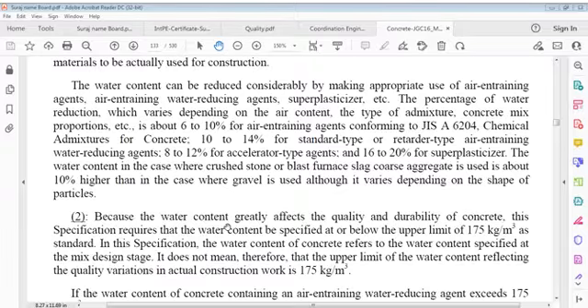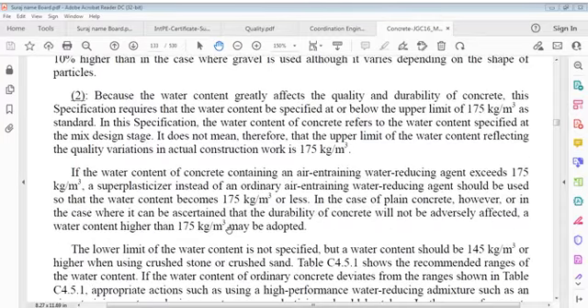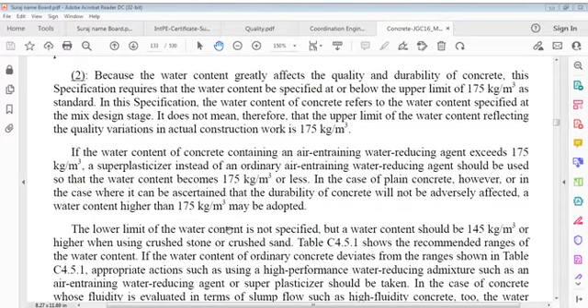Water content in the case where crushed stone or blast furnace slag coarse aggregate is used is about 10% higher than in the case where gravel is used, although it varies depending on the shape of particles. Because water content greatly affects the quality and durability of concrete, this specification requires that water content be specified at or below the upper limit of 175 kg per cubic meter as a standard.